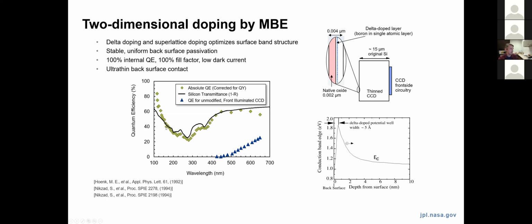And so I'm showing here just some quantum efficiency measurements of a CCD, in this case with no coating, that now shows 100% internal quantum efficiency. In other words, it matches the limit of the natural silicon reflectance throughout all of the UV and extending even into the EUV and soft X-ray regime ultimately.